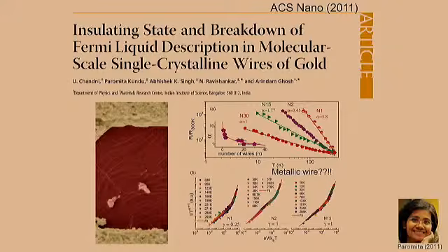And so the quick thing, without going into details, this was the paper that resulted from these particular measurements. Resistance versus temperature for a metal. You would think that the resistance is supposed to increase. That is the first simple thing that you think of, right? And when we do the resistance, the first thing that we see is that it's actually showing the reverse behavior. That is, the resistance is decreasing as a function of temperature. It also shows an interesting power law behavior when we do the measurements at different temperatures.